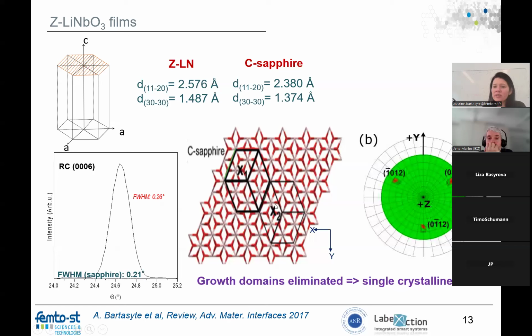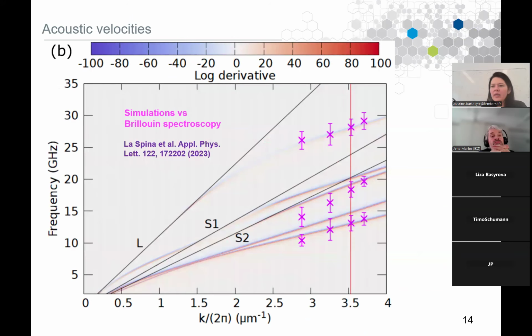But when the films grow on C-sapphire, we very frequently have 60 degrees rotated domains. So if you look at these three dense planes, they will be rotated by 60 degrees. In other words, it would exchange the X plus and X minus axes. So you rotate in plane just by 60 degrees. And the pole figure of the structure would have 6 peaks. But we optimized the growth to get just one single orientation with a nice rocking curve. We used these films as well to study Brillouin spectroscopy to check our elastic properties, if they fit.